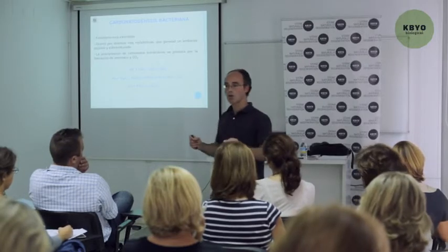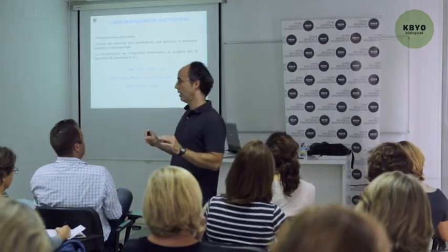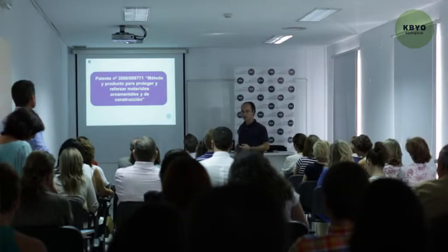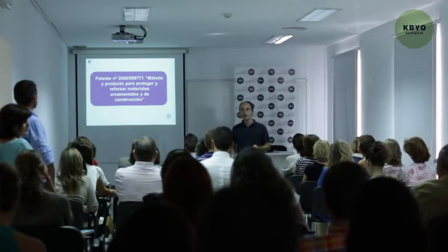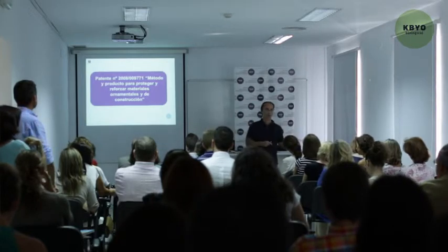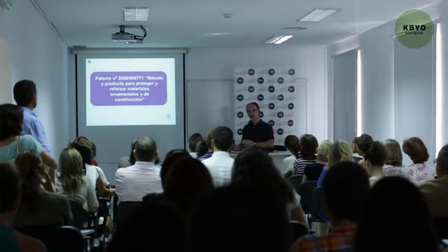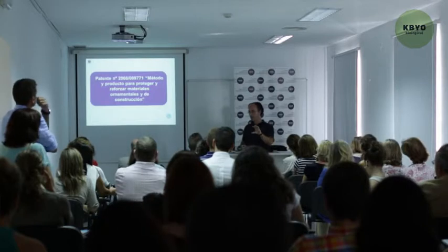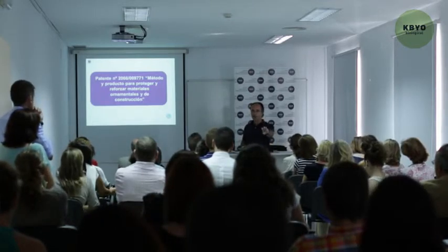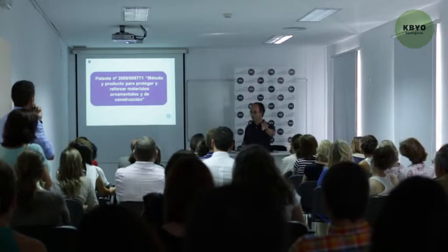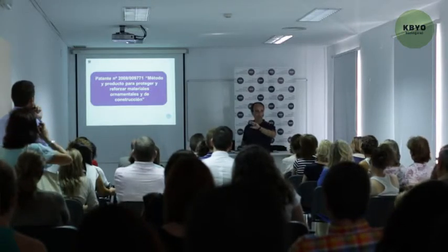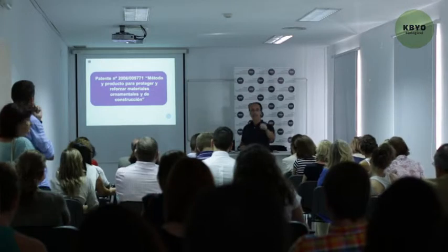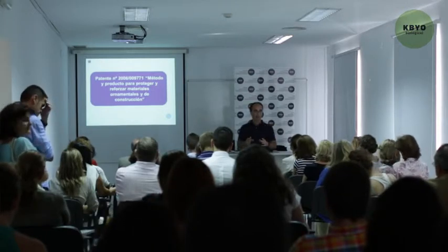Let's see some aspects of this treatment. Firstly, it must be proved whether ornamental rocks have a microbiota which can produce calcium carbonate, because we are not going to supply any bacteria. Detailed studies, including selective cultures and RNA analysis, have identified the phylogenetic sequence of those bacteria that appear in different rocks, and have concluded that 90% of those bacteria can produce carbonate.